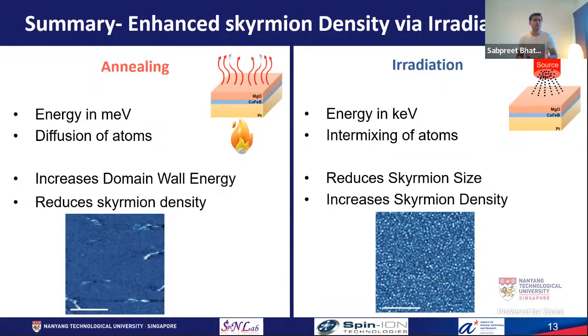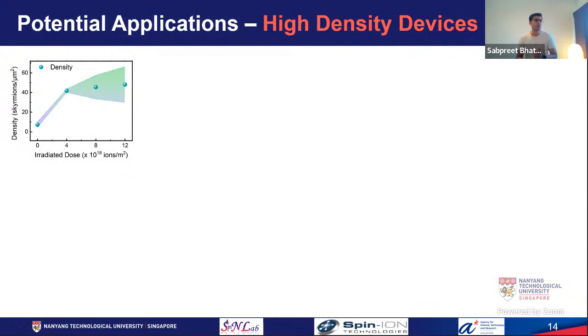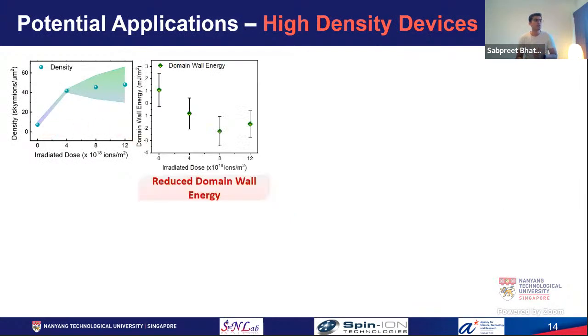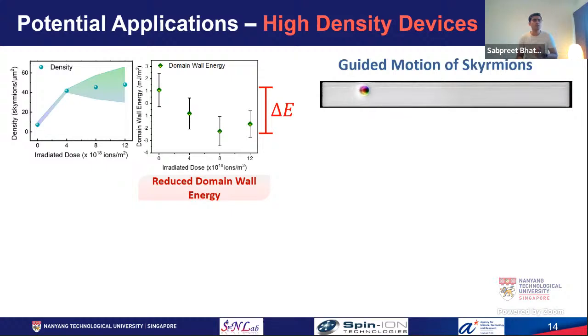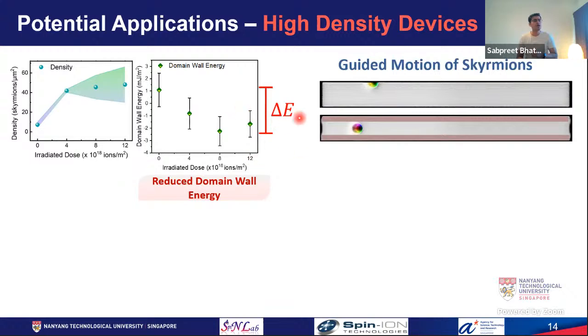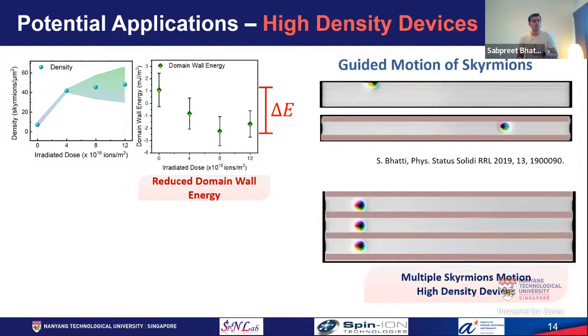Now, this irradiation can be used for further potential applications. For example, the increase in the skyrmion density can be understood because of the decrease in the domain wall energy, which gives you the delta E, the energy difference, which can be used for suppressing the skyrmion Hall effect. In normal skyrmion motion along the wire, it suffers from the skyrmion Hall effect, and there is some annihilation at the edge. Whereas if you use this ion irradiation, you can form energy barriers which will restrict the skyrmion along the edge of the wire, and you will be able to see a guided motion. This can be further explored for multiple skyrmion motions, where you can pack multiple skyrmions next to each other and can realize high density devices.